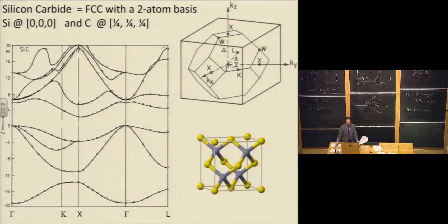And if you measure the curvature down at the bottom of the band near k equals 0, you get basically the mass of the free electron. It's not exactly the mass of the free electron, but it's pretty close, within 20 or 30% or so. So it really tells you that what's going on near the bottom is basically free plane wave physics, just perturbed slightly by the scattering potential that at the X point scatters you across the Brillouin zone and opens up this gap. Is that clear so far?